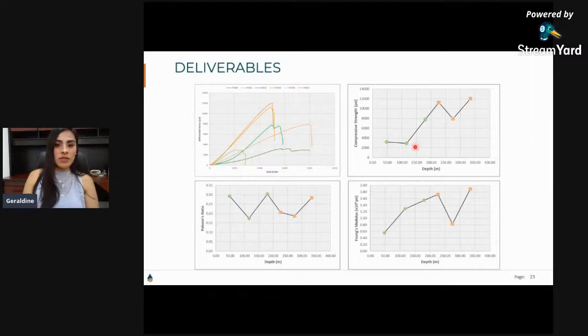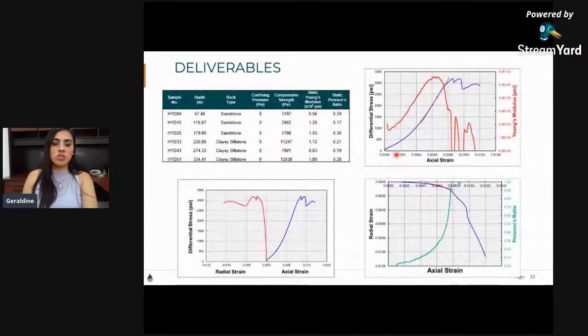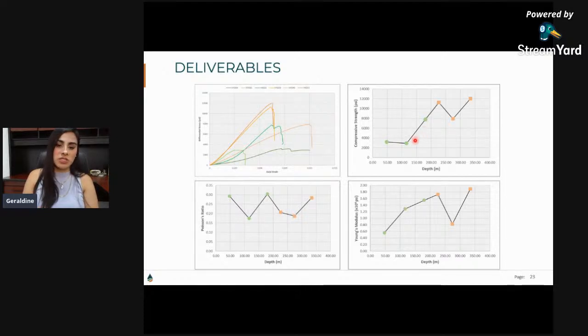What do these colors or differences mean? In this case, for this project, they represent the difference in lithology. You can see in the chart before, the first three samples were sandstones and the other ones were clayey siltstones. So the color is just to differentiate the lithology. These kinds of plots, this one is depth versus Poisson ratio, and this is depth versus Young's modulus, will help you to see if there is a trend in the parameter. In this case, you can see that at more depth, the samples increase their total peak strength.